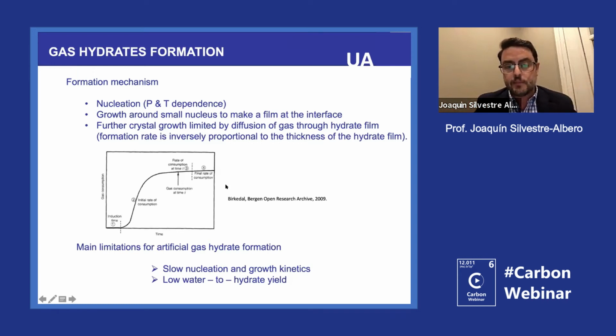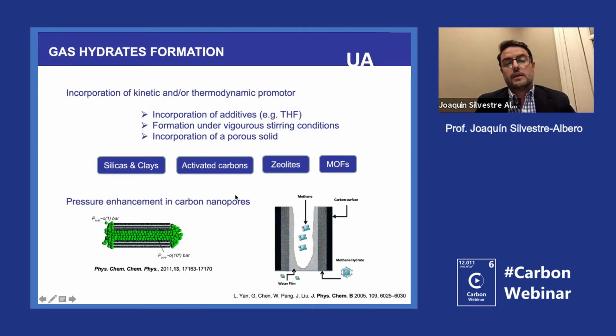So at the end, the people working with artificial gas hydrates in bulk phase have slow nucleation and growth kinetics, and they have a low water-to-hydrate yield because, as I say, once you make the first layer, you have a big limitation in the nucleation kinetics. That means that if you want to make them in a massive way, you have to modify the system.